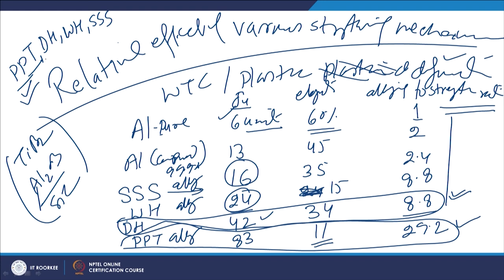Similarly, if there is a loss of the dispersed constituents, either due to fracturing or their dissolution, then this will cause a further severe loss of hardness. Thereafter, the loss of the work hardening effect due to recovery and annihilation will again lead to a reduction in strength and hardness. Minimum effectiveness is there for the solid solution strengthening.